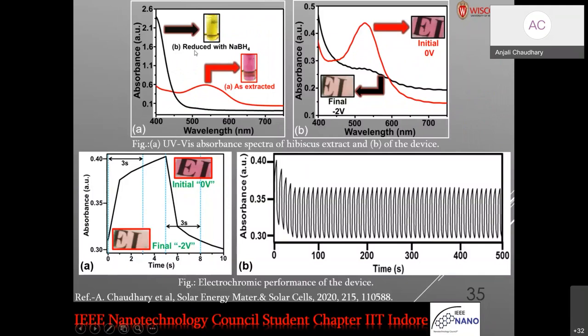And this is the UV-Vis spectroscopy of the as-extracted and NaBH4-reduced hibiscus flower solution. And this is the device UV-Vis. You clearly see that initially at 0 volt, it is magenta, and there is a maximum absorbance peak at 520 nanometer, which corresponds to the magenta color. And when you apply -2 volt, it absorbs all wavelengths nearly equally, and thus appears nearly transparent to our eyes.